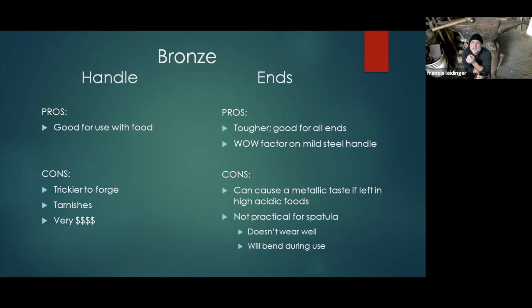The only downside to bronze, it's trickier to forge. It's a little bit more temperamental, and I kind of treat it like copper. I forge it at about a good solid red, and when it starts to get cold, I stop. I don't want to risk hammering on it too cold, and I really don't want to risk hammering it too hot. It'll fall apart on you. It pretty much just disintegrates if you overheat it. That's the downside, or one of the downsides. So you really got to proceed carefully, especially if you're going to use a coal forge. If you have a gas forge with a thermostat, then you just set your number to the forging range, and you're good to go.